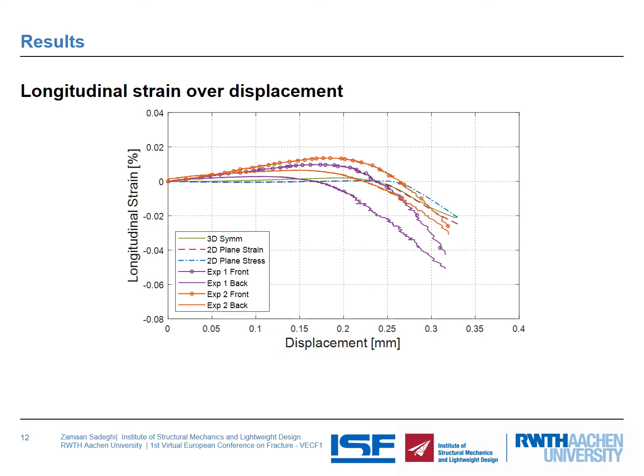In addition to that, you can see, for example, for any individual experimental test, if you consider experimental 1, there is not the same trend for a strain gauge which is mounted on the front side and the back side of the single lap joint. So due to different reasons that we can consider later, this can be a normal behavior in single lap joint, that the crack does not start at the same time from both ends of the single lap joint, and that's why we don't expect a symmetric crack propagation and consequently the similar strain variation for front and back side of the single lap joint, as we expect in our FE analysis, which is basically a symmetric crack propagation.